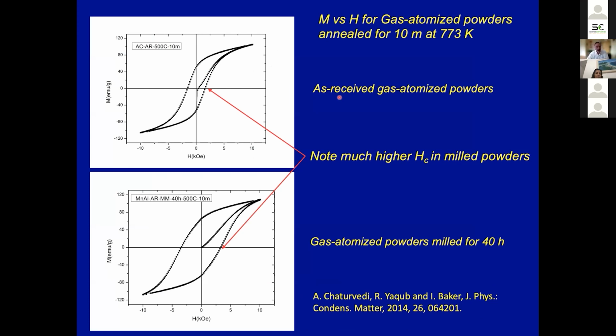And in fact, here's the data for gas atomized powders, where we've taken those powders and simply annealed them and measured the magnetic properties, and we get this hysteresis loop. And this is when we've taken those gas atomized powders, mechanically milled them, so they've got a very fine grain size, and then annealed them in the optimal conditions. And you can see in this particular case, we've got essentially the same saturation magnetization, but a much larger coercivity in the material.